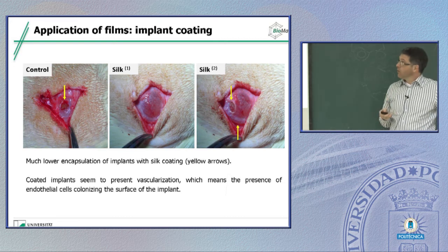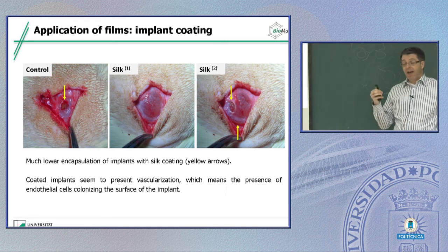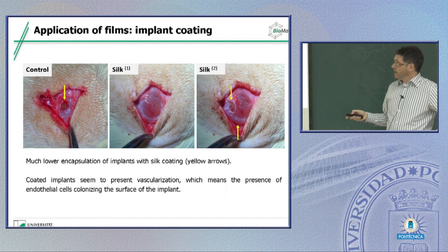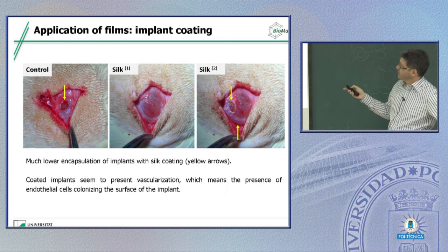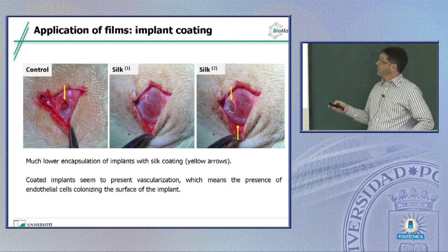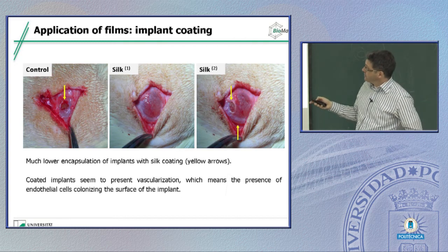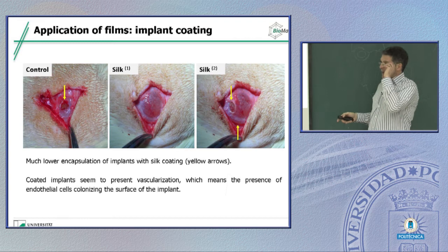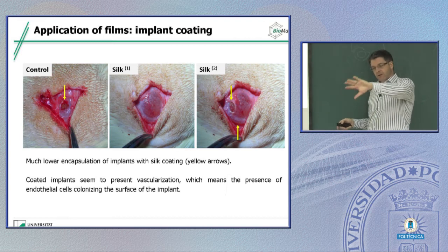Well, one finding was that we saw a dramatic reduction of the fibrosis, meaning no encapsulation. Here you see just 2 out of 45 whatever animals. This is how typically such an implant looks like after 3 months. And 3 months is sort of like the critical time point. I mean, typically fibrosis occurs in the first 3 months.